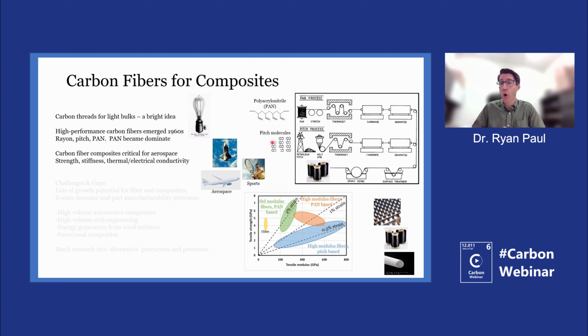The pitch-based carbon fibers, because of the long-range graphitic structure that can develop, can give a good thermal and electrical conductive fiber and composite. But they also have different properties from a stress-strain perspective. And so this chart quickly illustrates where the different carbon fiber precursors tend to fall. They're all, quote unquote, carbon fibers, but they're very different depending on the precursor.